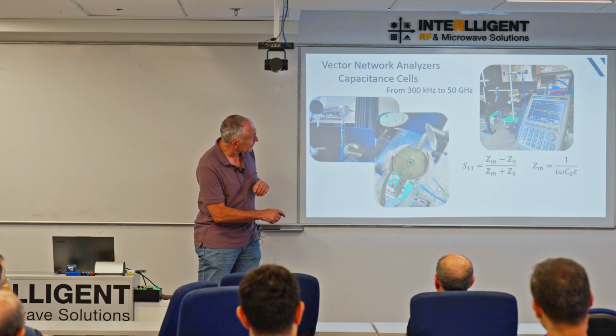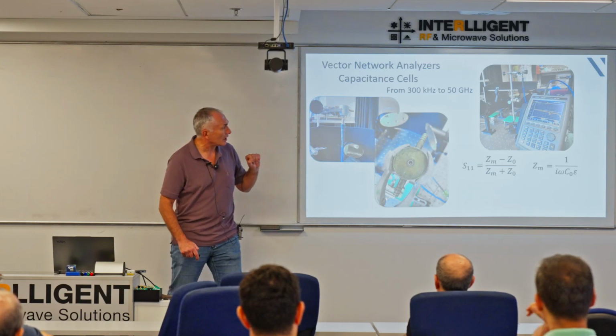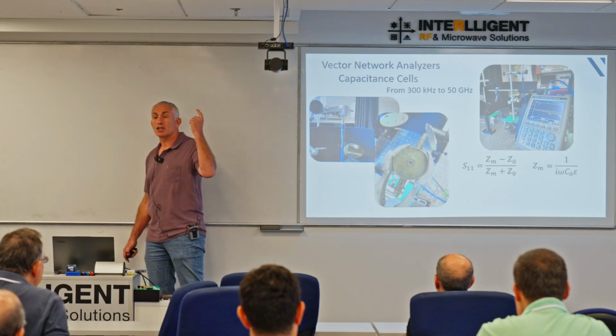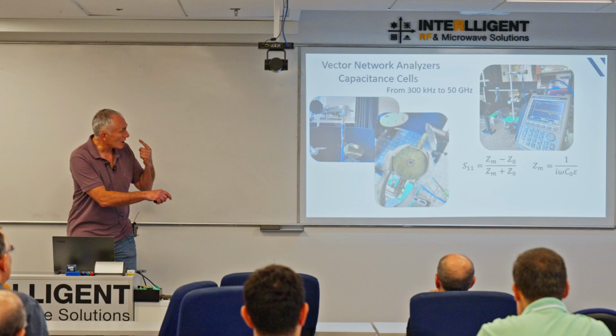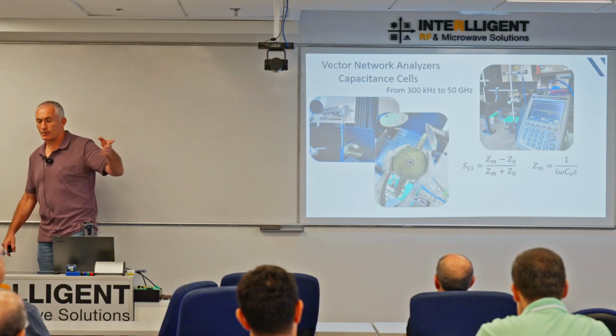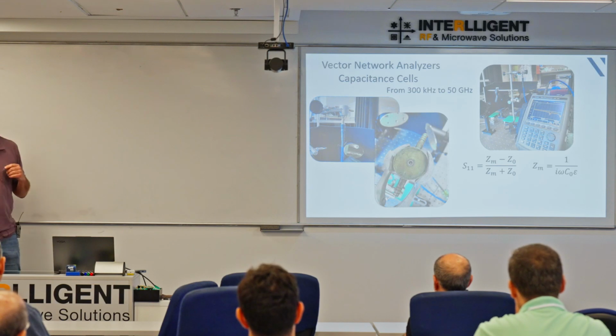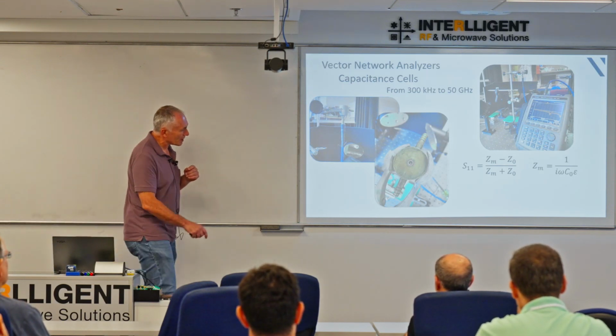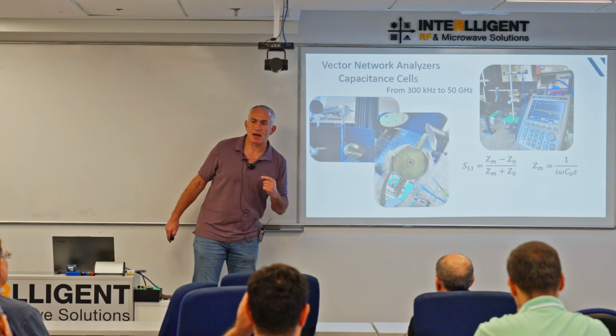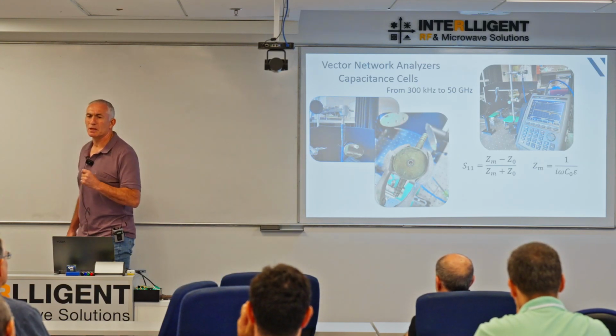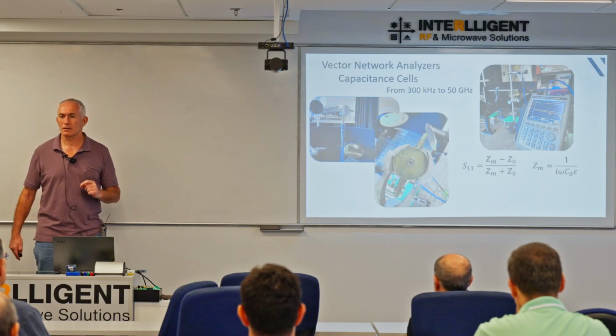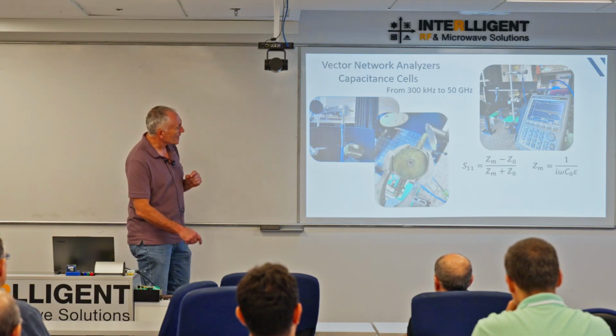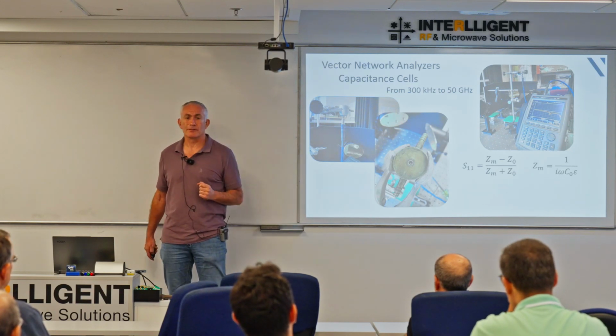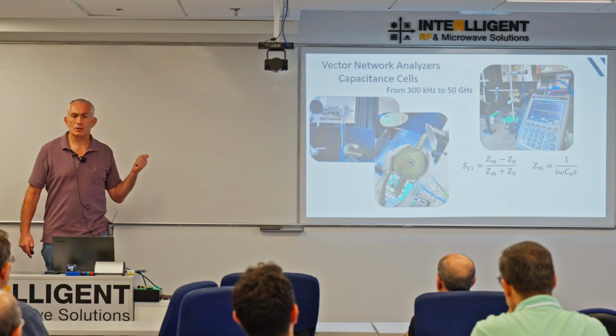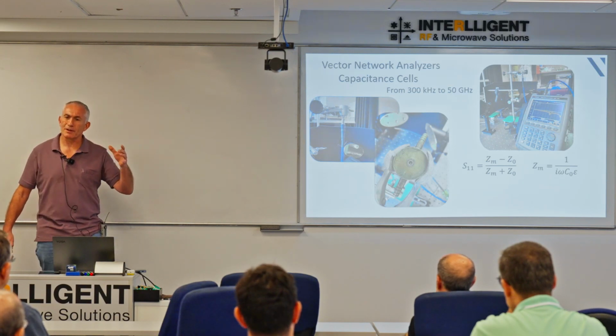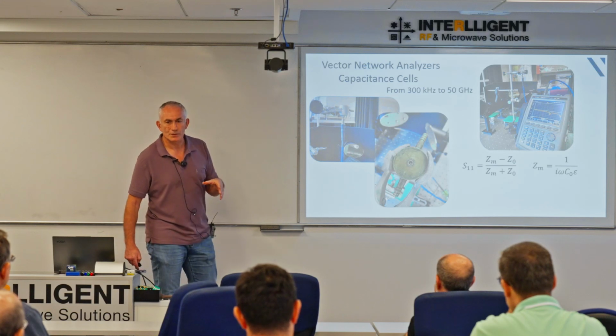Now, I've set up here, in this particular picture, this is an S11 measurement where we've terminated the line with a simple sample cell. These sample cells were developed by Yuri Feldman all the way back in the 90s. So that's a cylindrical cell with a very small electrode there inside. This diameter is about 3.6 millimeters. The inner electrode is about 2 millimeter diameter. The electrode length is only about 1 millimeter, 1.5 millimeters. Now, it's a small volume, microscopic volume in fact, but with that you can measure water, you can measure blood, you can measure all sorts of very interesting things, liquids of all forms.